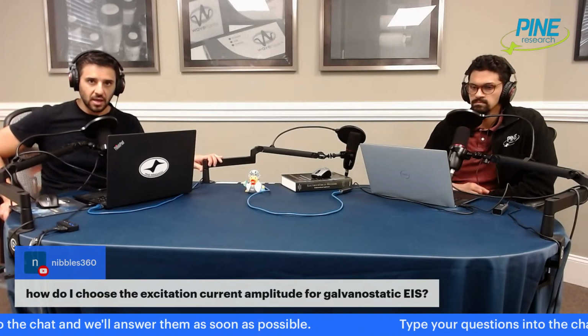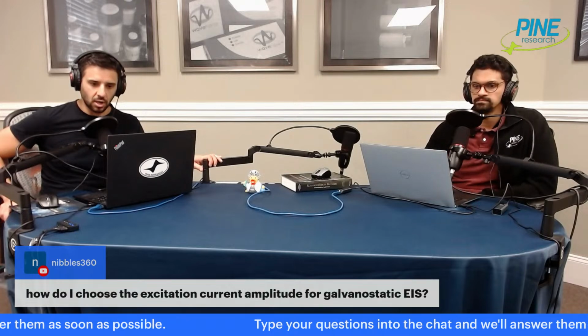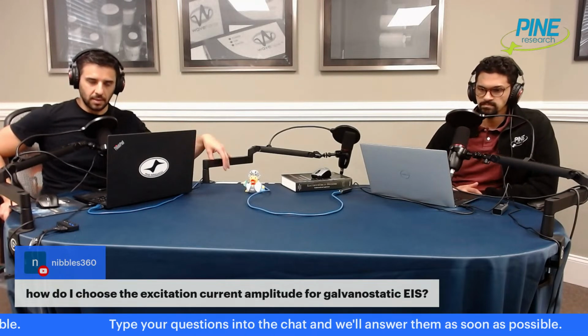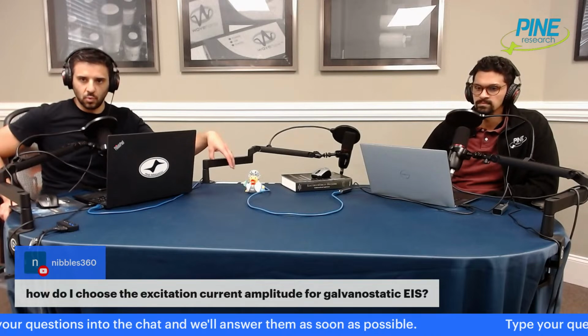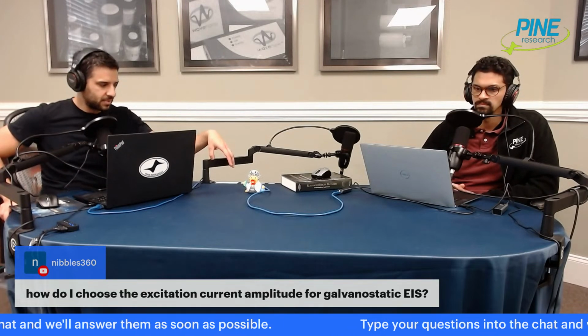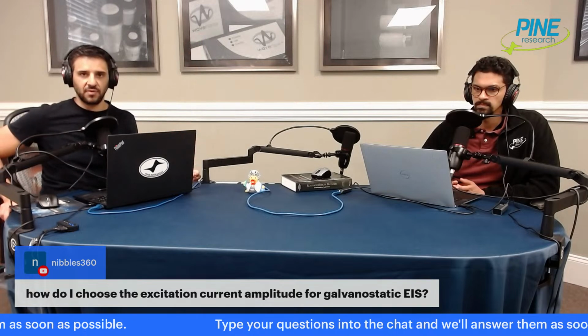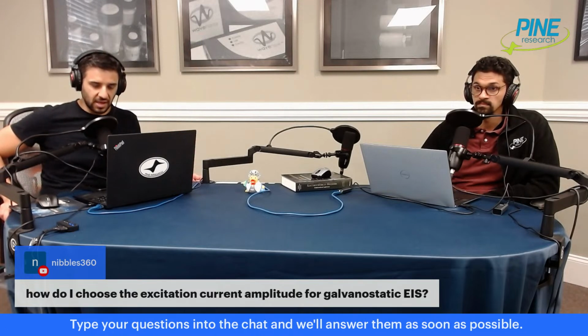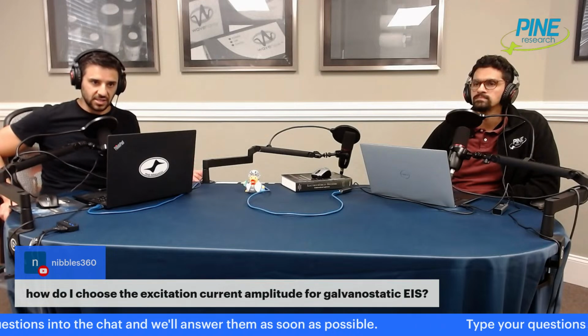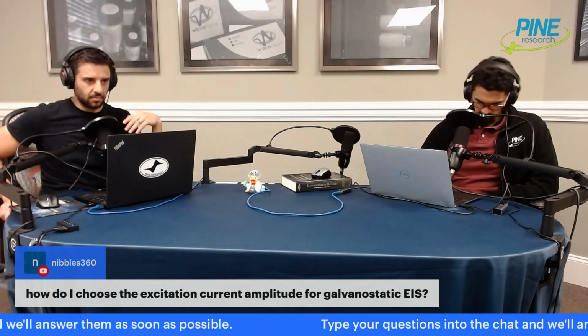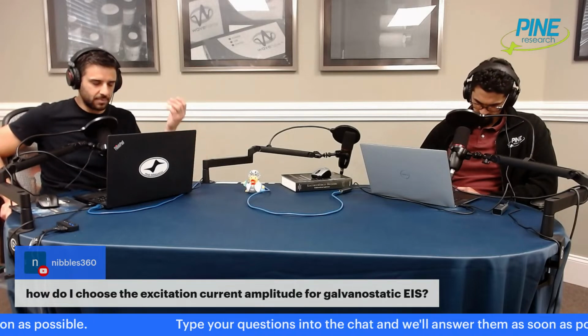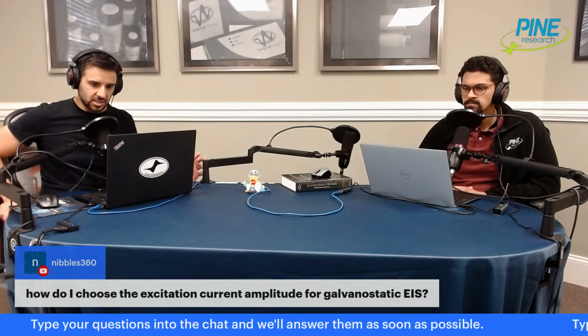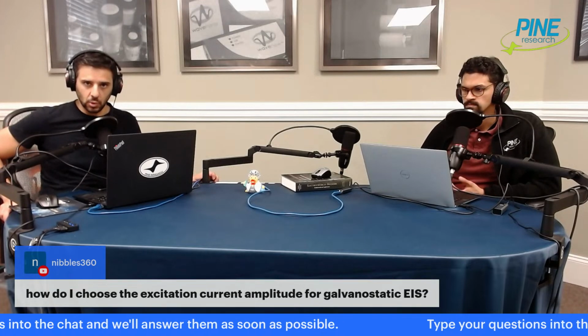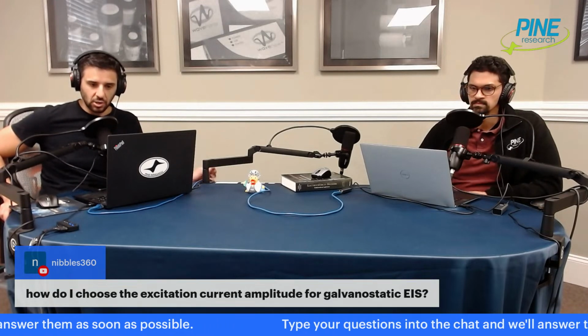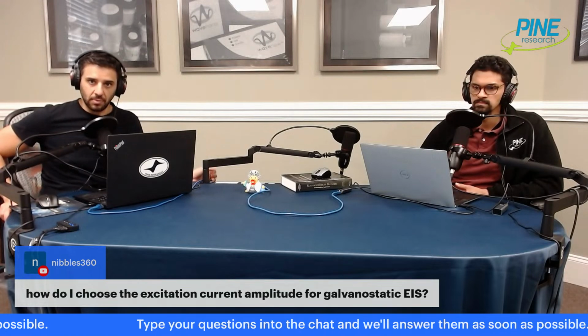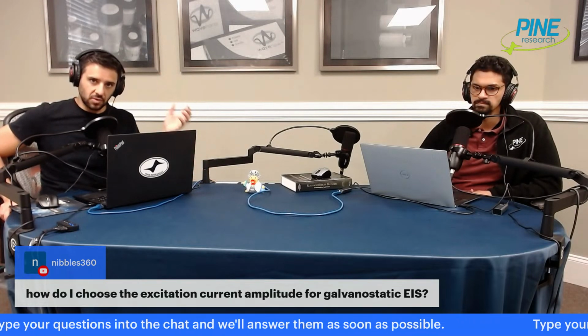If it's not a battery, my advice is, generally speaking, start with something very small. Probably not nanoamps, like most things won't respond at all to a nanoamp, but again, it depends on the size of your electrodes, what system you're studying, how big it is, how much current it gives you in a normal experiment, for example. But a small percentage of the normal amount of current you would measure in a normal experiment is where you should begin. If the data looks terrible, slowly increase the amplitude until you get a reasonable signal.